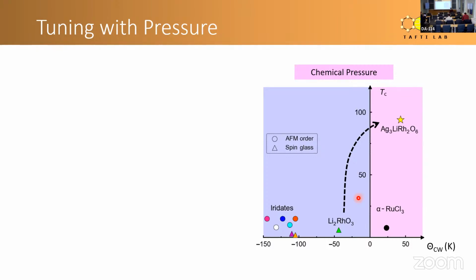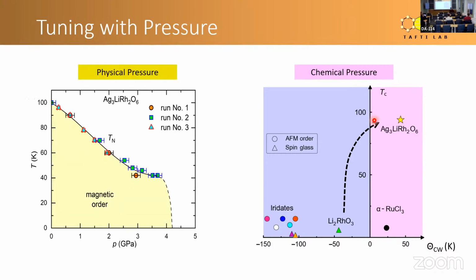Now, so this was of course an experiment. You can call it a chemical pressure experiment or some kind of a chemical experiment where we change the behavior of the material by changing the atoms between the layers. But now what we ended up having was a material with a relatively high antiferromagnetic transition at around 100 Kelvin. So in the latest project, we decided to get this material and pressurize it and see what happens, because pressure is another tuning parameter, and see if we can tune back this material to where it came from, if it is possible or not.